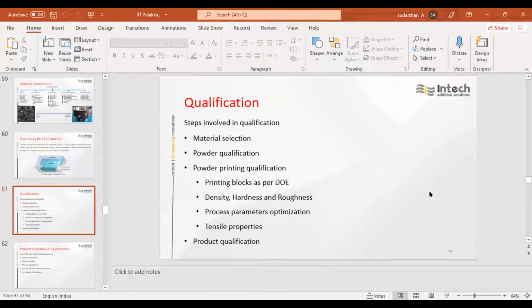Okay sir, if spot diameter from the machine is taken, remaining all the parameters are material related things. Like when selecting the hatch spacing, it's nothing but related to the diameter. For a given laser spot diameter, there is a curing zone. If the laser spot size is very high, the curing zone is also very high, then the hatch spacing will be selected accordingly. If spot size is bigger, the penetration will be more, so layer thickness also depends on the spot size. So machine specific is nothing but from the machine side, specifically what we need to take is laser spot diameter. Fine sir.